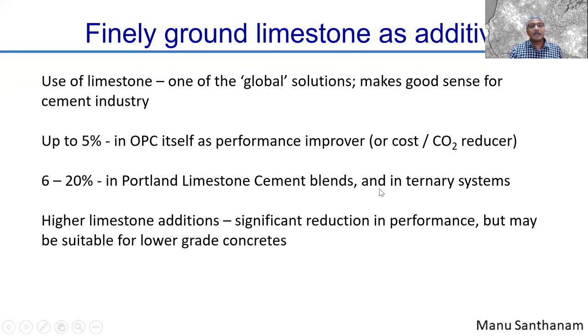Then there are countries where Portland limestone cement blends have also been popularized. In India also, the standard for Portland limestone cement is under preparation, and we expect that this will also be available in the future as one of the types of cement in the industry. And here, the cement is replaced up to 6 to 20% by limestone. More popularly around the world, you have 15% replacement of clinker by limestone to make Portland limestone cement. Okay, and if you see articles from Canada and Europe, you'll see that a lot of the construction projects have actually utilized Portland limestone cement for all kinds of applications.